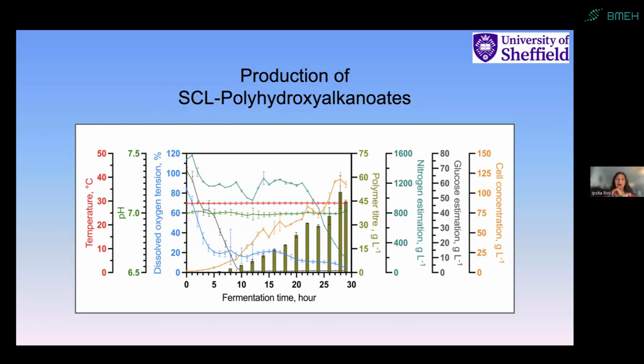You can see that with time, the green bars are increasing. That is, the polymer yield is increasing. The bacterial cells are growing, as you can see with the orange profile, and overall it is a highly controlled process. This is one main reason I use fermentation for the production of natural polymers rather than isolating them from a natural source. I have exactly controlled conditions, and therefore the polymer that is produced has the same molecular composition and molecular weight, and this is essential, as you might appreciate, for any biomedical application.